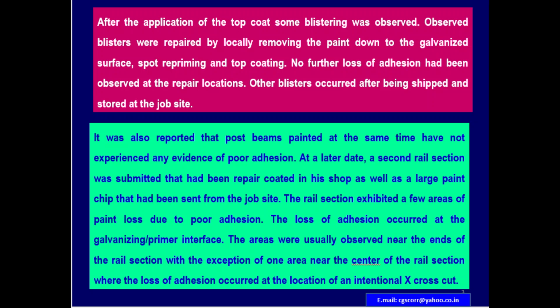Observed blisters were repaired by locally removing the paint down to the galvanized surface, spot repriming and top coating. No further loss of adhesion had been observed at the repair locations. Other blisters occurred after being shipped and stored at the job site. It was also reported that post beams painted at the same time have not experienced any evidence of poor adhesion.